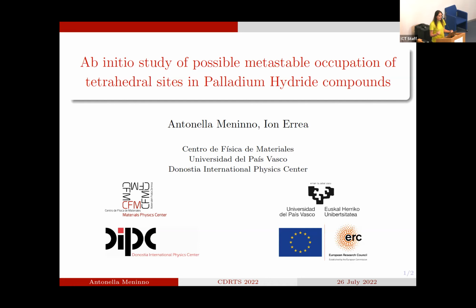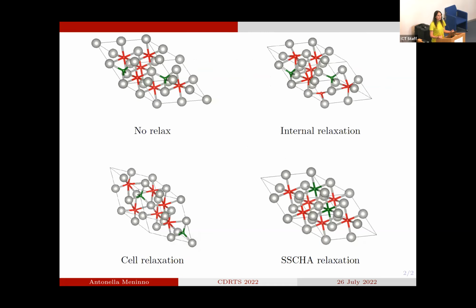We know that palladium hydride in its full octahedral configuration has been studied already, but what I want to do with this work is to basically study other possible configurations of these palladium hydride compounds. So basically, what I did was to choose randomly some configurations. So we know that the hydrogen can stay in an octahedral site or in a tetrahedral one. Here in this figure, in which it is written non-relaxed, the hydrogens in octahedral configuration are colored in red. Instead, the hydrogens in tetrahedral configuration are colored in green. So basically, I classified many of those structures according to the number of tetrahedral and octahedral sites that they occupy.